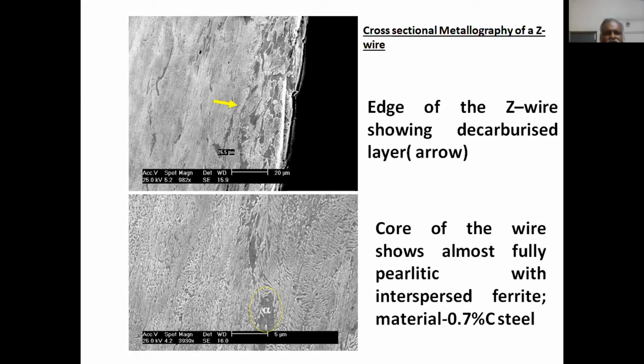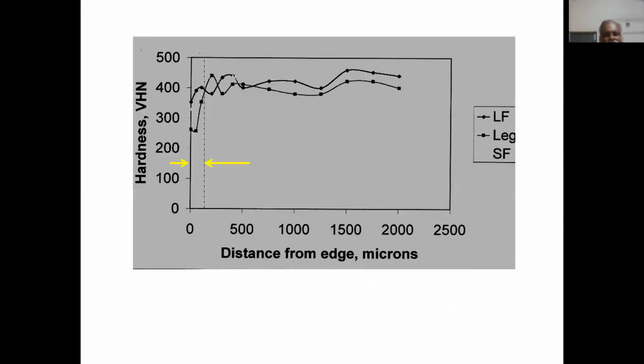Let it happen, mechanical engineers told me. Let it happen. What is so great about it? We have 64 millimeter, several wires are there, sir. Nothing will happen with this 20 micron of decarburization. In fact, decarb is permitted as per the American Wire Rope Association. So I continued further. I showed the mechanical properties. You can see clearly that a hardness map across the thickness shows that the edges exhibit 200 VHN compared to the core, which is around 400 VHN. Correct? So that means what?